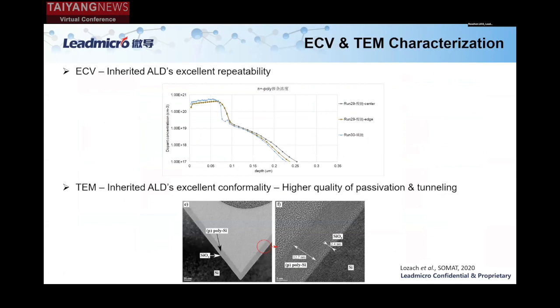Here are some characterizations to further illustrate the advantage. As you see from the ECV, we can achieve very good uniformity and repeatability even on G12 size wafers. For the TEM image at the bottom, you can see that even with ultra thin silicon oxide around 2 nanometers, we can do a very uniform deposition even along the texture surface. This shows that it inherited the ALD's excellent conformality. This also means you will get a higher quality of passivation and tunneling.